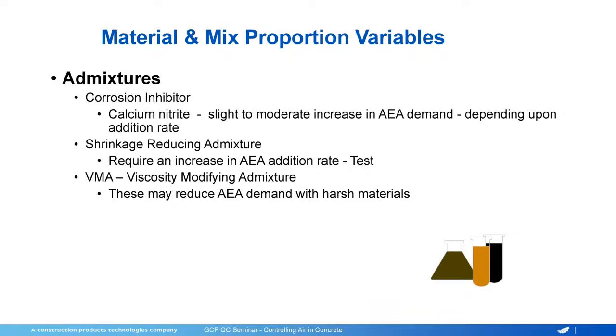Corrosion inhibitors, like accelerators, they can impact it slightly. And again, if you're using a corrosion inhibitor with a hot water, that can be an issue. Shrinkage reducing admixtures, that can be a bit all over the place. Some of them you cannot get air with, so you would have to be very selective of the shrinkage reducing admixture that you're going to use, and then test to make sure you can get it. And again, don't put the air in the same time the shrinkage reducer is going in.